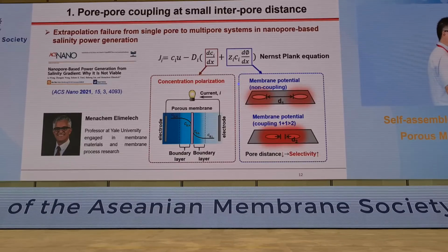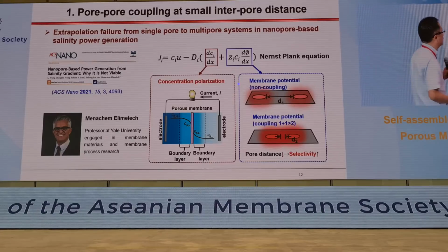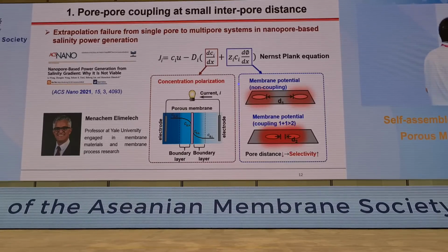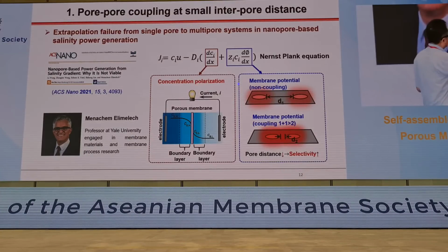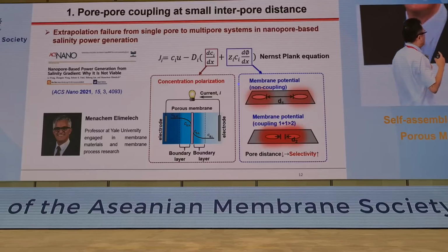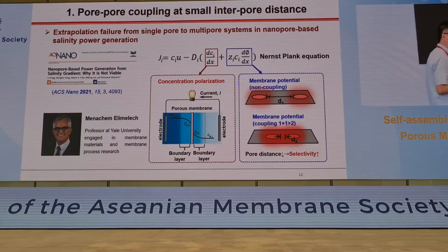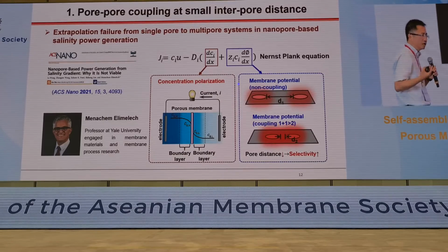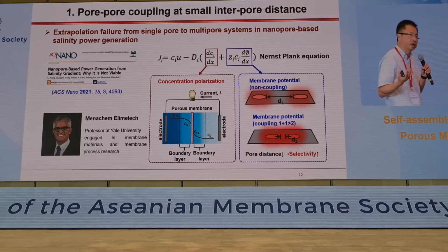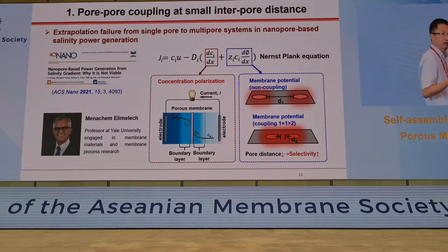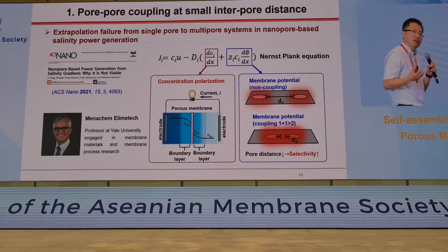When you increase the pore density from the single pore system to multiple-pore systems, you will find a stronger so-called concentration polarization effect. That means across the membrane, it is harder to maintain the concentration gradient. As a result, such a strong concentration polarization effect has been believed to be an insurmountable bottleneck for salinity power generation.